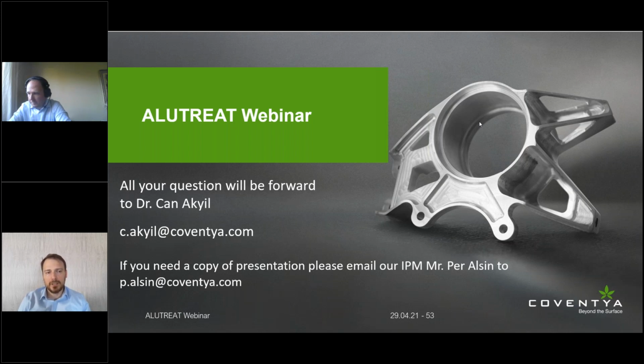Secondly, oxalic acid is only one type of organic acid that helps out with the process for a certain amount of time, especially at the start, by lowering the aggressivity of sulfuric acid. But in order to maintain the productivity and also the broader parameter window during anodizing, one could introduce more. Therefore, the 557 is actually a blend of several organic acids with different carbon chain lengths.